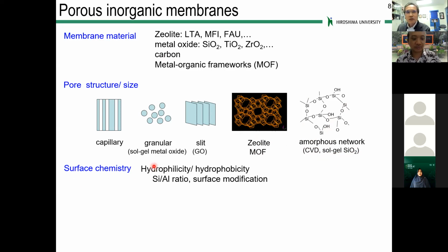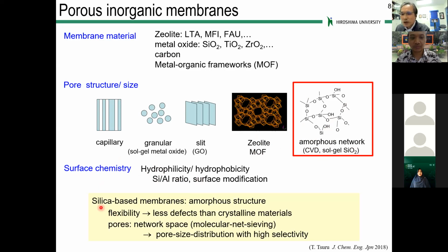Of course, the surface chemistry is very important to control the hydrophilicity and hydrophobicity. Our research team has been working on silica-based membranes with this type of amorphous structure. We believe this type of amorphous structure has a flexibility which will lead to fewer defects than crystalline materials such as zeolite and MOFs. And also in this case, pores are formed as the network space. So that's why I call this molecular net sieving. We need to agree that these membranes have a pore size distribution, but we would like to say, okay, with high selectivities. Now I'd like to share with you some recent progress of our research activities, okay?